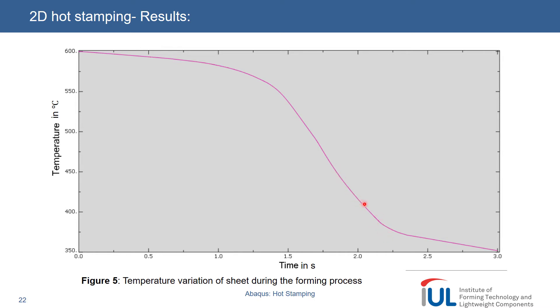From the point of actual contact when release starts, you go into a transition phase where gap conductance again dominates heat transfer, and from there you go back to fairly linear cooling as seen in the beginning, because linear behavior is typical for radiation to ambient. It's quite interesting - technically it's logical - that we see this S-curve: linear, then gap conductance, then actual true contact conductance between the sheet and die, again gap conductance, and then again linear due to radiation to ambient.